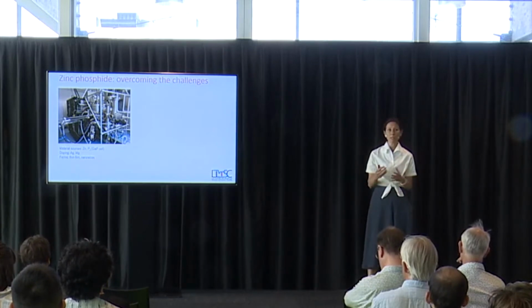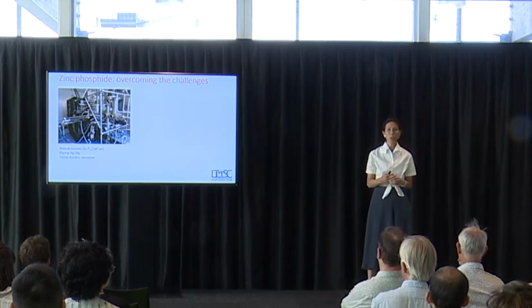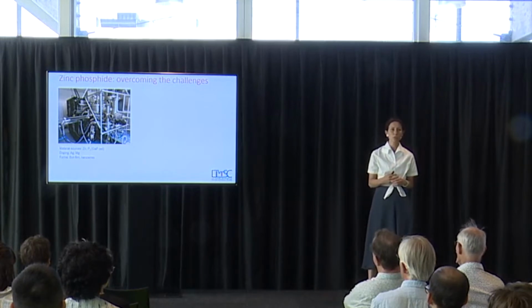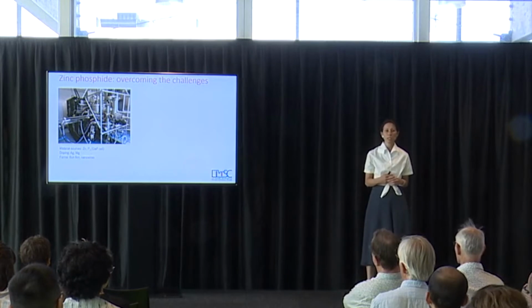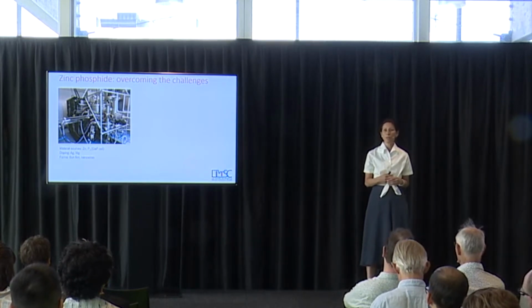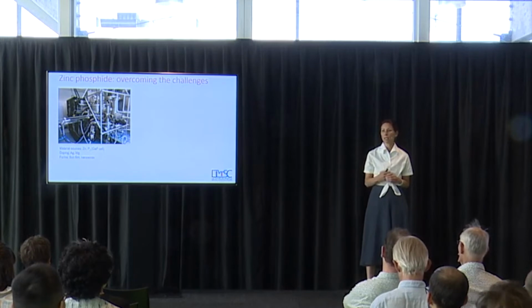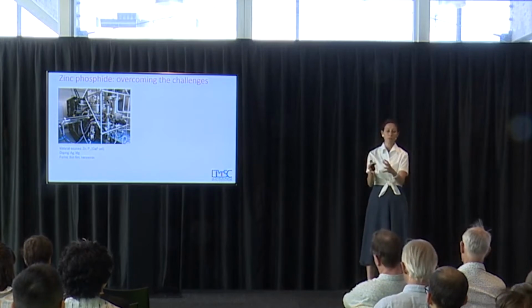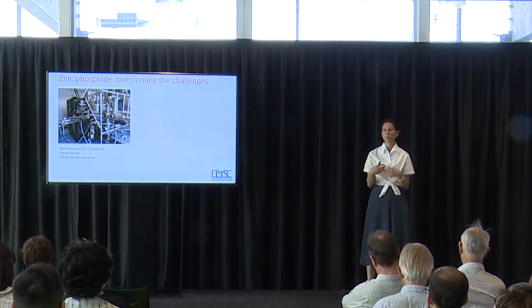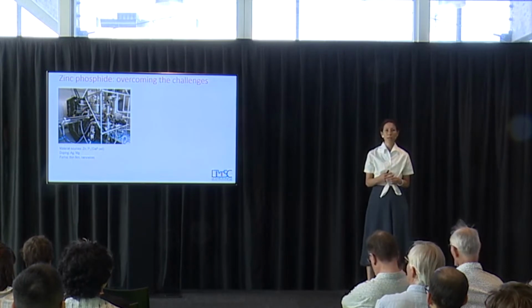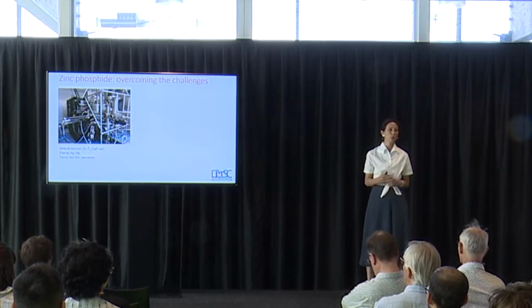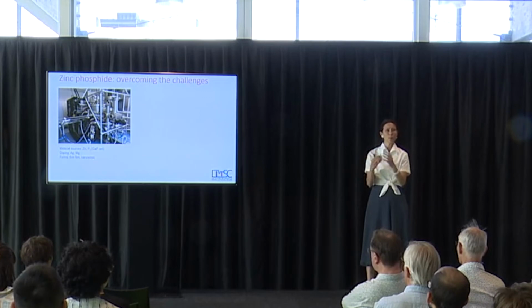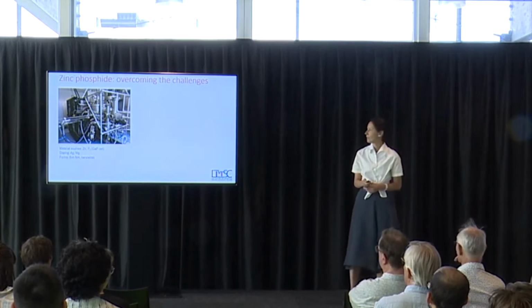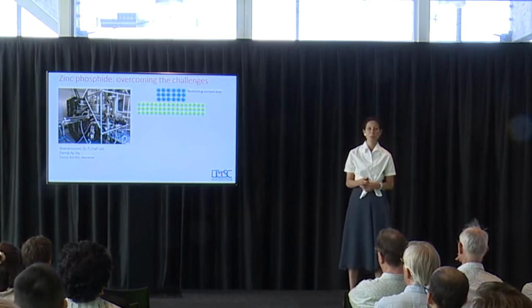We evaporate zinc, and we evaporate P2 from gallium phosphide. And the reason is that phosphorus is a highly inflammable material, especially in the P4 form. And so typical molecular beam epitaxy machines with phosphorus would have a big bucket of phosphorus that they would evaporate and try to transform the P4 into P2. It made me very nervous to have a bucket of phosphorus in my machine. So what we do is we have gallium phosphide, it sublimates P2 directly, and the gallium stays in the cell, so like this, everybody is happier, including me, and the students too.